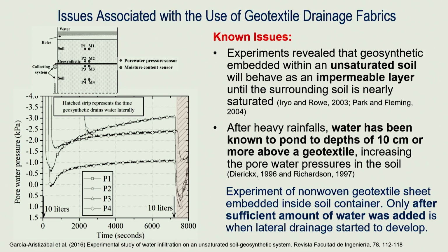So we have a couple of moisture sensors above and below, and also a couple of pore pressure transducers, trying to get some sense of what is happening as we add water to the system. So you add 10 liters of water, and no water is transported. And you keep on adding water until you reach a certain threshold, in this case about 20 liters of water.